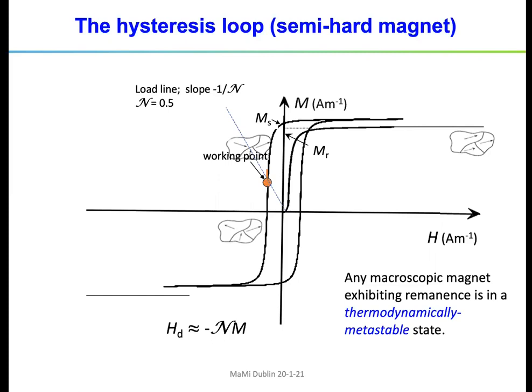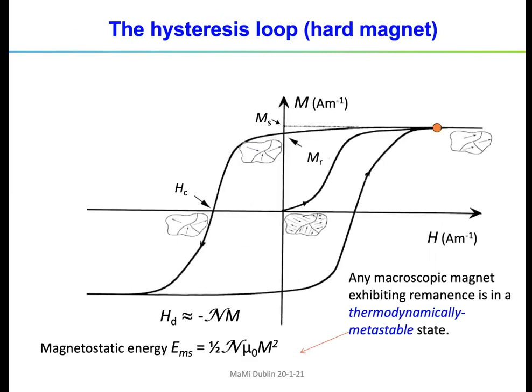So what we need to have an effective magnet is a material with a fat loop, right? So we can go right over there, where the magnet, of course, operates in the second quadrant where M is positive, but H is negative because the magnet is sitting in its own demagnetizing field, which is minus N times M. So there's the working point. And provided we can get a nice square loop, sufficiently broad with a hysteresis, a coercivity greater than 0.5 of the magnetization, we can produce a real magnet, which we can make in any shape we like.